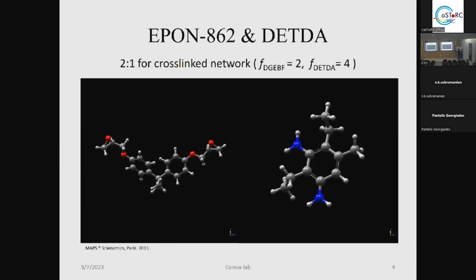But in epoxy resins, the polymerization happens with the help of another molecule, which is the hardener, in order for the cross-linking process, which is the polymerization process, to happen. As a hardener, I chose this molecule, called DETDA, and it has functionality 4, due to the 4 hydrogen bonds that the amine types are able to create.